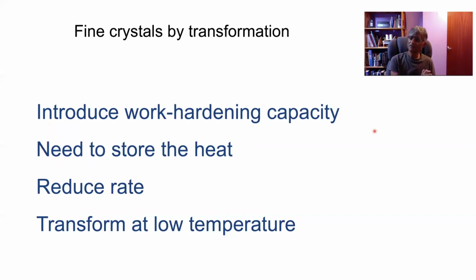We've done it with the TRIP steels, for example, where a small amount of retained austenite in the microstructures transforms at stress concentrations and gives work hardening, and therefore we get a large elongation in spite of an increase in strength. Okay, so in summary, if we choose a displacive transformation, then it would have to be bainite because we are talking about the ability to produce large samples, which you cannot uniformly quench without adding huge quantities of alloying additions. And we need to avoid distortion associated with rapid heat treatment.